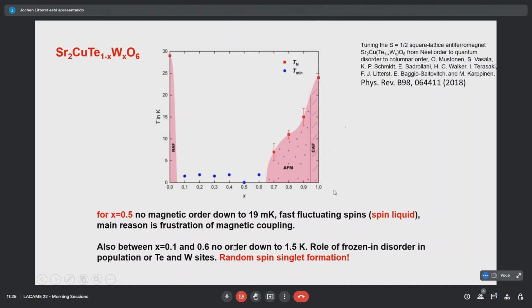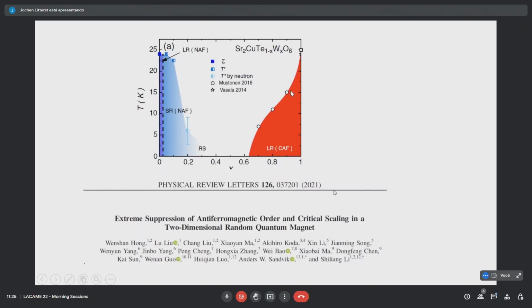The reason for that, from much more recent experiments and theory, is random spin singlet formation in this area. And for sure, we have disorder here just from the mixing of the two compounds. So it's not only at one concentration where we have frustration, but over a larger range. So the newest phase diagram looks like that. That's our data. Our data also claims that there is some kind of short range order which extends to higher concentration, and here in the middle, as we already found, there is no order at all, and we're really in a spin liquid state.